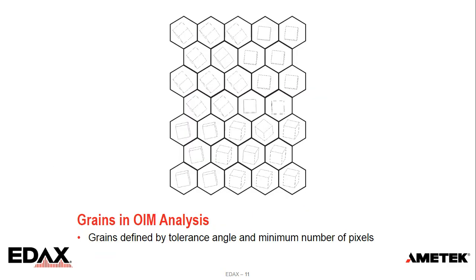Once we have those orientations, what we do with EBSD and with OIM is we typically calculate grains. And when we talk about grains, we define a grain in terms of a tolerance angle and a minimum number of pixels. So if we have our measurement grid, and we typically measure things on a hexagonal grid, this puts more of a packing factor of measurement points on a specific area. And each point has 6 equidistant neighbors. So we can sample more neighbors of the same distance for local kernel measurements. We'll talk about that when we talk about some of those metrics.